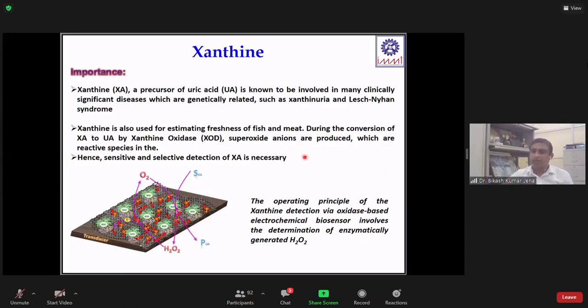So as this nanoparticle modified electrode shows better response towards hydrogen peroxide than what we thought, let us utilize it to develop some oxidase based biosensor. So what we did, we assembled xanthine oxidase, another enzyme, which converts xanthine to uric acid. At the same time, the oxygen present inside the solution is converted to hydrogen peroxide. The hydrogen peroxide that is generated can easily be oxidized by this platinum nanoparticle on the graphene surface and provide the electrical signal to the electrode. So this system was used for detection of xanthine.